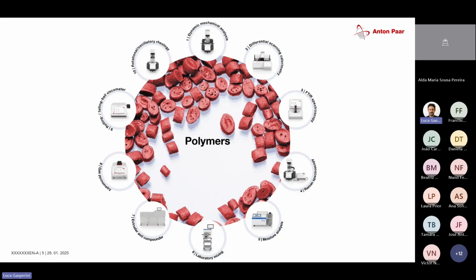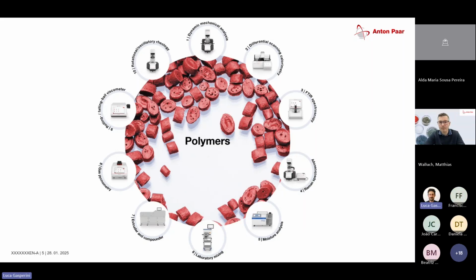Then I have something unique, but not as often used: Raman spectroscopy. A quick question, who of you is using Raman? Really? Graphene? Okay, this is a prime example. So yeah, the main struggle with Raman is that FTIR is the much more potent solution for polymers, but there are some applications where it actually makes sense to use Raman. For example, if you're working with hydrogels, which have a lot of water in them, typically the water peaks would overlay the whole FTIR spectrum. So in this case, with Raman, you actually get much better results. Or if you're working with graphene, this also works very, very well.